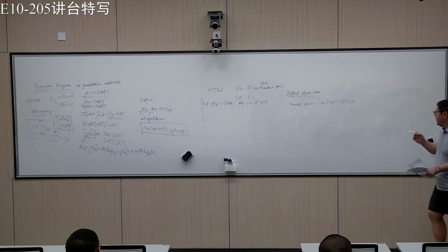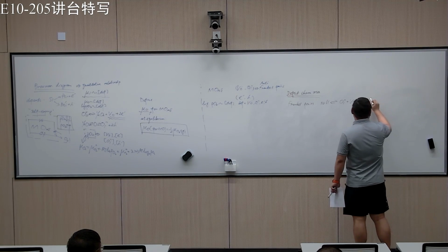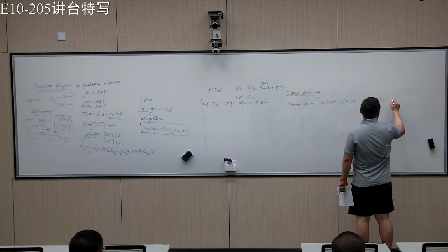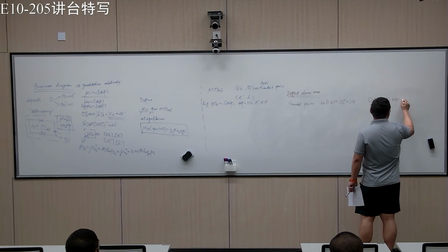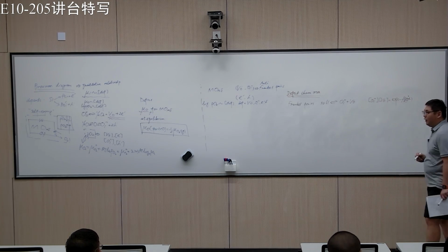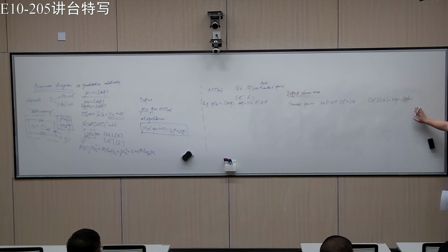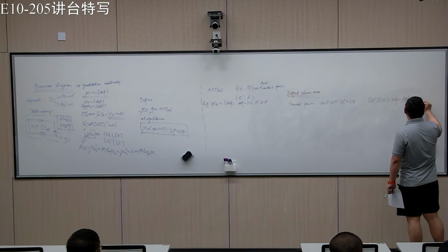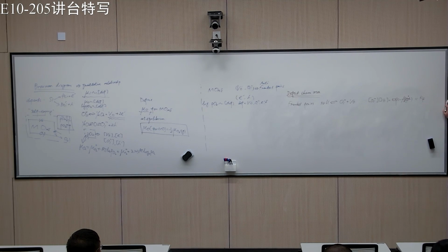If we reach equilibrium, we can write that it should be exponential of minus mu Frenkel over RT. However, here in the Brouwer diagram, we don't change the temperature. We fix the temperature. If that's the case, we just say it's some kind of chemical equilibrium constant, KF. So this is the first equation we have.